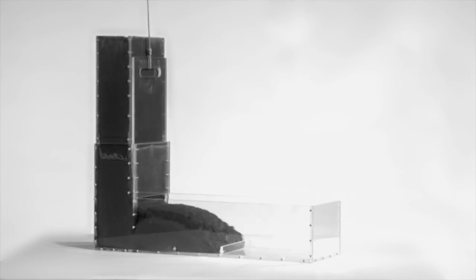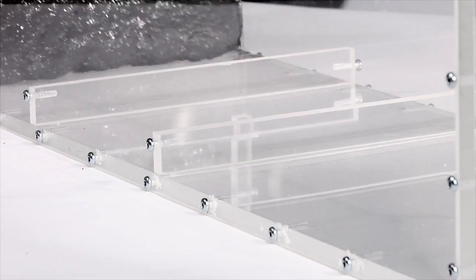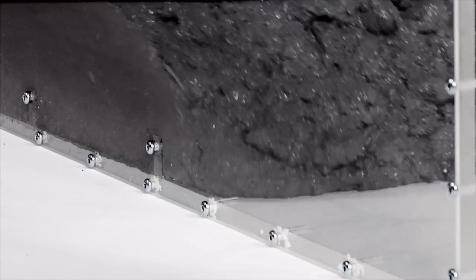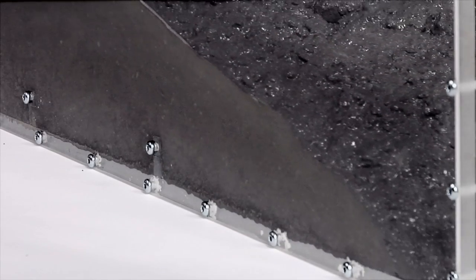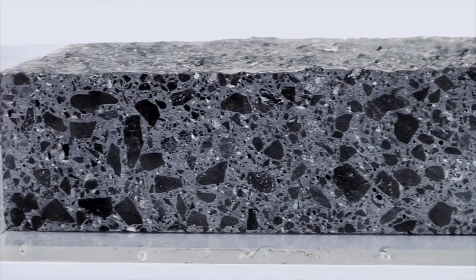The other measure is called the L-Box. 20 liters floats out and passes obstacles like reinforcement steel bars or plates, or as in this case, two plastic bars. The concrete flows over and around the obstacles easily.